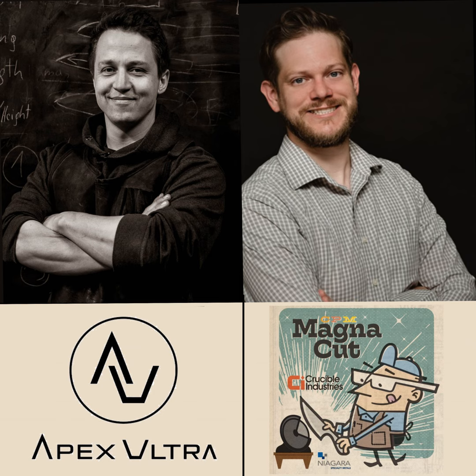Absolutely. That's great. One thing about the grits that I often encounter is which grit to send to. If you want a really dark edge, especially if you want to darken out a monosteel blade, or you just want a really dark edge on your nickel Gomai blade, don't go crazy high on the hand sanding. I generally recommend something around 800. Baker, you said, is recommending 600. 800 is plenty, because if you go to 1500, 2000, whatever, you can do it quickly, but it actually makes the edge less stable in my experience. So I prefer something like 800 and then the ferric and then the orange juice, and then I'm happy. And that makes a very stable oxidized layer.